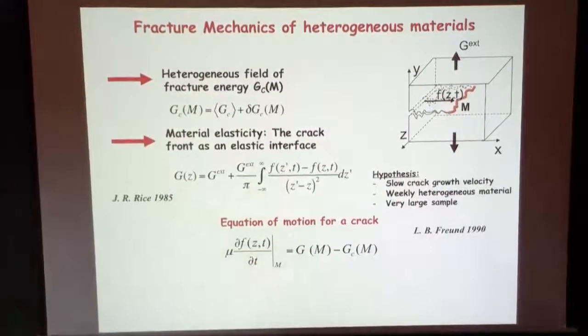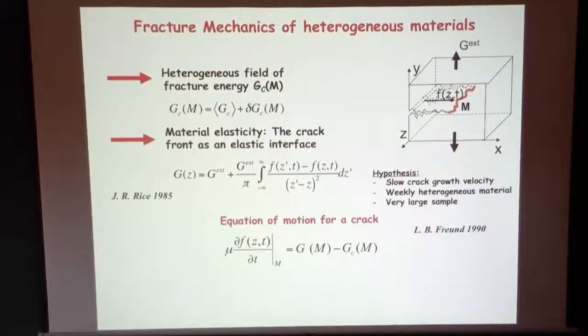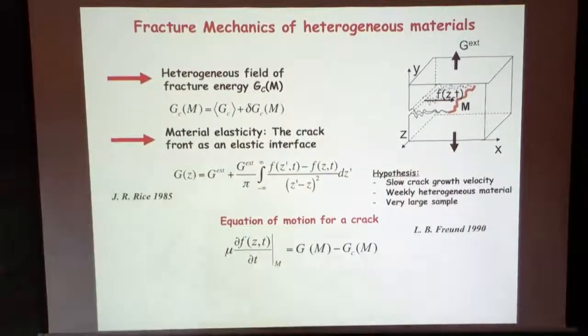It's also a practical law. It's over dynamics. So for many reasons you're going to pick up this kinetic law that actually does a rather good job, as we will see in the following. It's also somehow consistent with the equation above, because the line tension is calculated assuming that the entire stress field is able to equilibrate before the contact line moves. Right? It's effectively a quasi-static limit.